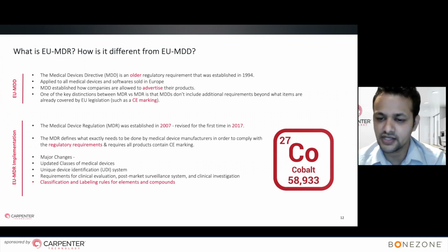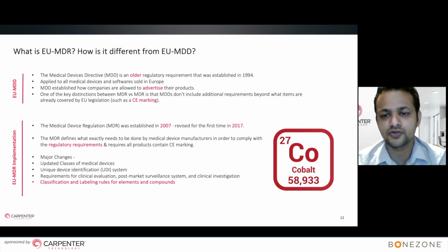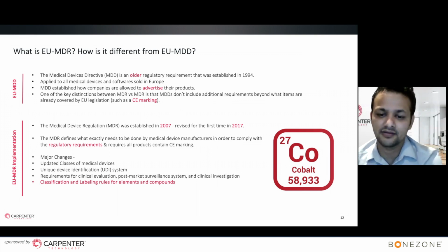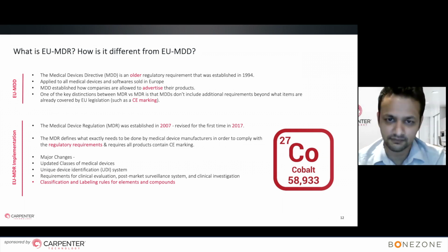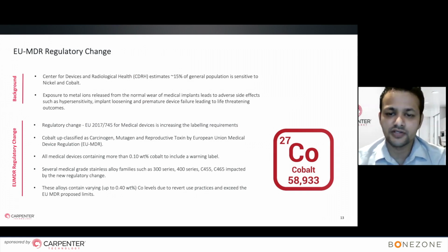But in this instance, in 2017, there was a unanimous vote to essentially upregulate or upclassify cobalt to a class 2 CMR component, which essentially means that cobalt or cobalt containing devices will have a much tighter scrutiny. And the reason why that happened was essentially, if we go back and look at the background and the physiological landscape of why that change was effected, we see that more than 15% of the general population is sensitive to nickel and cobalt. So there is a growing concern with respect to metal allergies. And cobalt being one of the elements, again, is a point of concern, especially when it leaches out from a medical device,